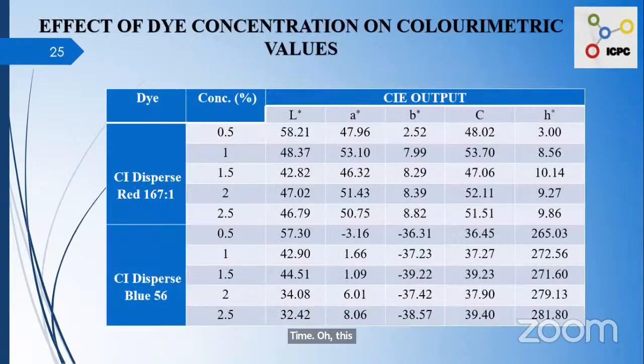So this is the table for the effect of dye concentration on colorimetric values. This table shows that a decreasing lightness value with increasing concentration of both dyes is evident, indicating an increase in color depth. For red dye, the a value is negligibly changing and the b value is increasing with increasing dye concentration. This shows that the red dye builds slightly yellow as the concentration increases, whereas for the blue dye, the a value is increasing and the change in the b value is negligible with increasing dye concentration. So this shows that the blue dye builds slightly redder as the concentration increases, whereas the chroma remained similar with increasing dye concentration for both dyes.